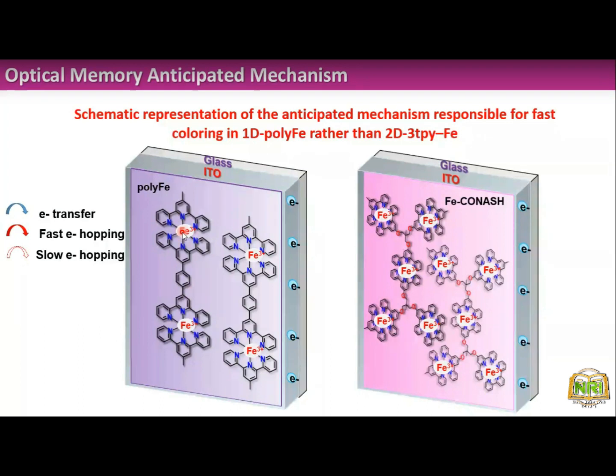Because there would be some diffused electrons or diffused ions in the gel. I told you that we are applying the gel because of the ion conductivity. There will be some trapped ions, and at the same time on the electrode there would be excess electrons, right? So when the film is in the iron 3+ oxidation state and we disconnect the device, the excess electrons staying on the electrode will go. This is called electron transfer and electron hopping. Electron transfer as well as electron hopping from one center to another center through the conjugated structure is very high. So when the electron transfer happens, automatically iron 3+ will reduce to iron 2+, and it will immediately form a color. It comes back to the original color.